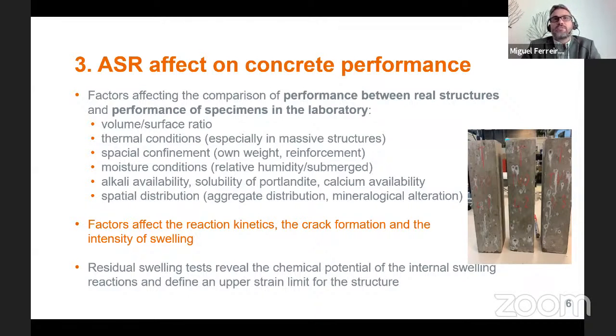And if we think, for example, on one hand, we have a rather small lab sample. On the other hand, we have a 1 meter thick large wall. What is the volume to surface ratio of these two? What are their thermal conditions? How are they different? What is the spatial confinement by own weight, by reinforcement? What are the moisture conditions? What is the alkali availability or the solubility of portlandite or the calcium availability and the spatial distribution of the